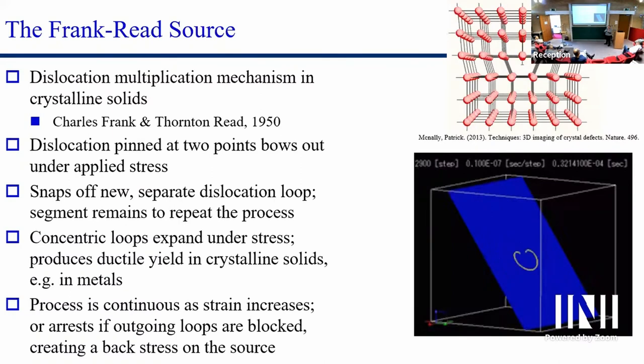And so you get one more atomic spacing, and one more atomic spacing, every time a loop comes out. And if there is a free surface, those loops will expand and annihilate on the free surface, making permanent plastic deformation. However, if they get stuck, there's a back stress. So they interact with each other, they repel, there's a back stress that shuts down the source. So there's a limit of crystal plasticity.